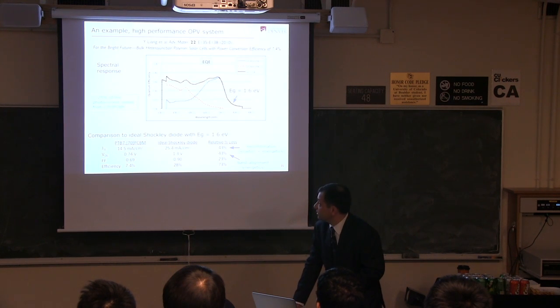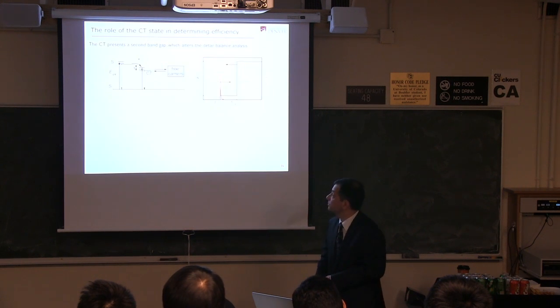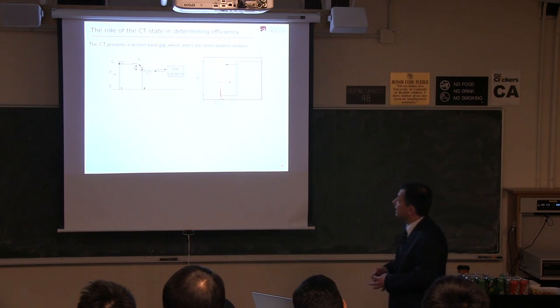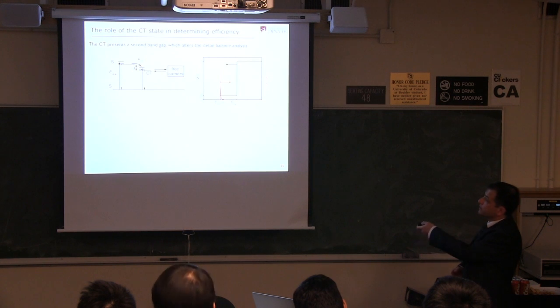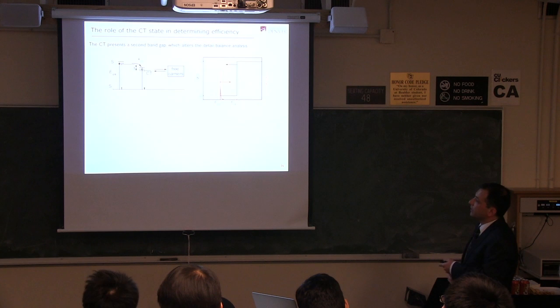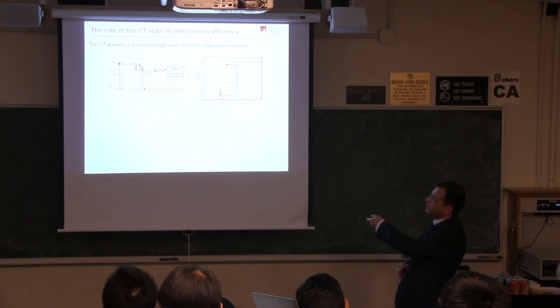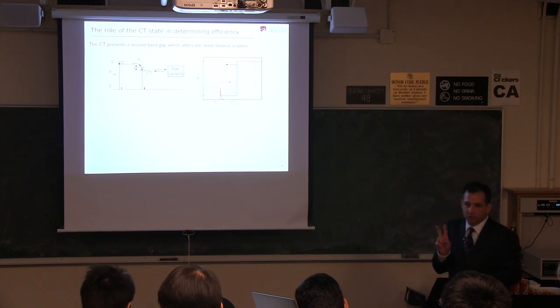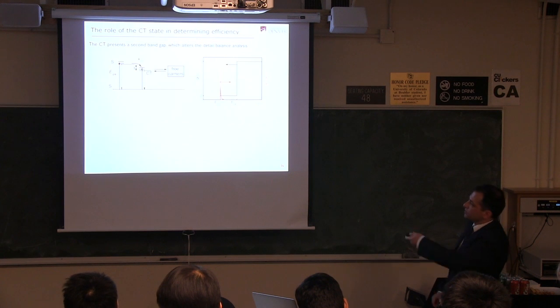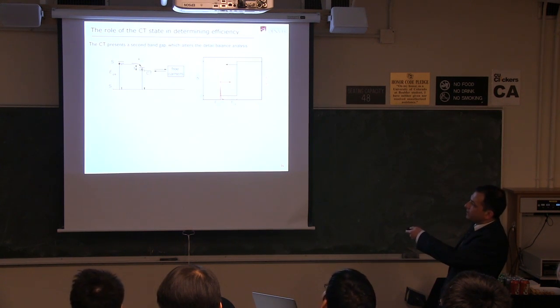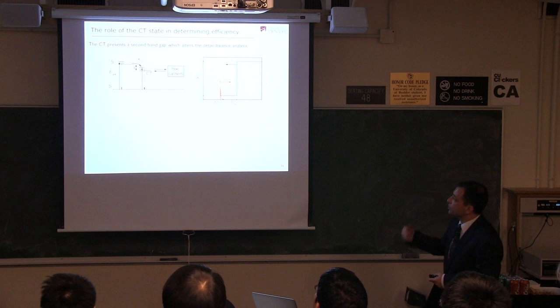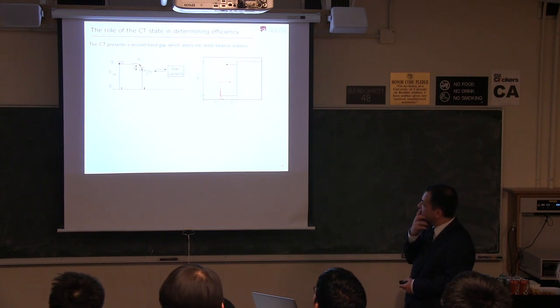Okay, so I want to talk specifically about that charge transfer state, that CT state, because that's very important. Now, so again, in the state diagram, we absorb into the S1 state, create the CT state. Now, the CT state can itself luminesce. That means that there are effectively two band gaps in the material. There's an absorptive band gap and an emissive band gap. And that changes the thermodynamic calculation.